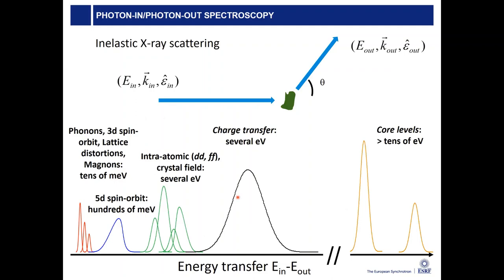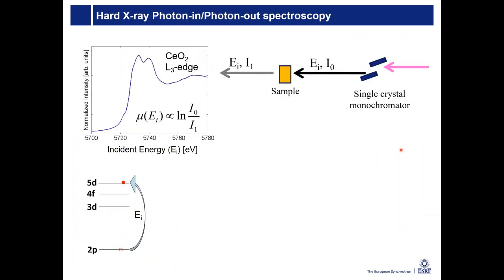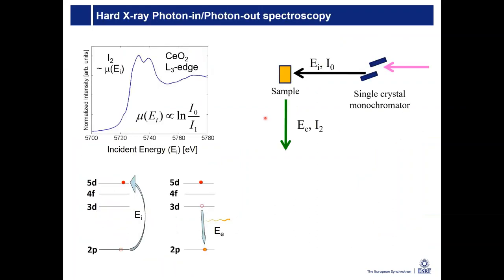Another way of showing this is just an overview, so you can study using this inelastic X-ray scattering by reducing the energy transfer. You can see phonons, you can see crystal field interactions, you can study your charge transfer excitations, and if you go to higher energy transfers, you see then core levels in your inelastic scattering process. Now I give you an example for cerium dioxide to see how this works. So excite 2p to 3d to 5d in this case.